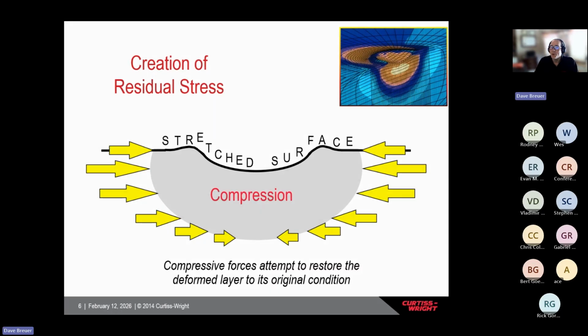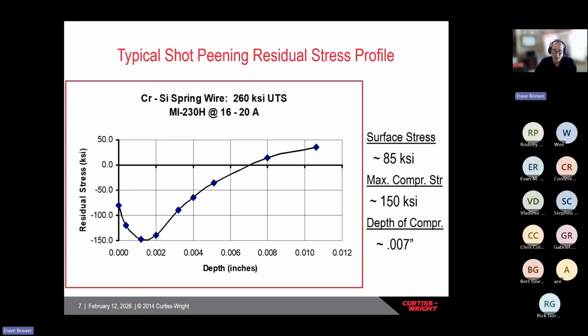So if we were to measure the residual stress, this graph happens to be for a spring wire, a 260 KSI spring wire. This graph plots residual stress on the vertical axis as a function of depth. Zero is the surface, and this goes into depth. Compressive stresses are defined as negative, so more negative implies more compressive stress magnitude.